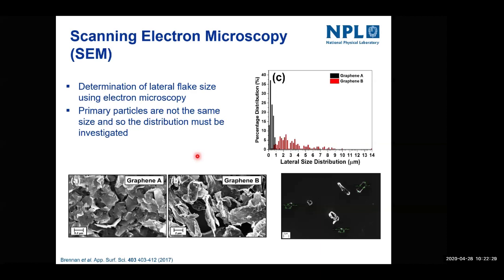And if you see here on the top right, you can see these very different distributions of lateral sizes of these flakes when you look at hundreds of flakes with this technique. And again, if you look at the bottom here, taking our example of graphene A and graphene B from before, although these look similar, the scale bar is actually an order of magnitude different. So again, there's a very big range here depending on where you get the material.